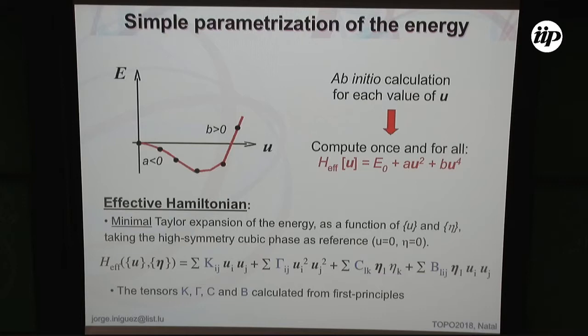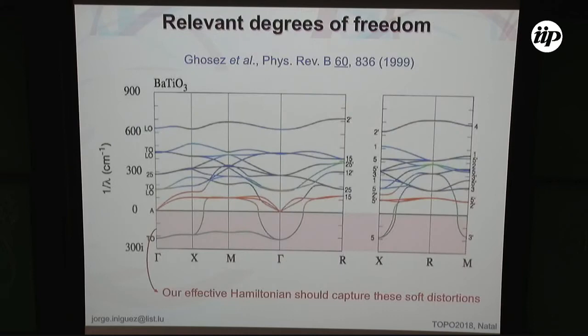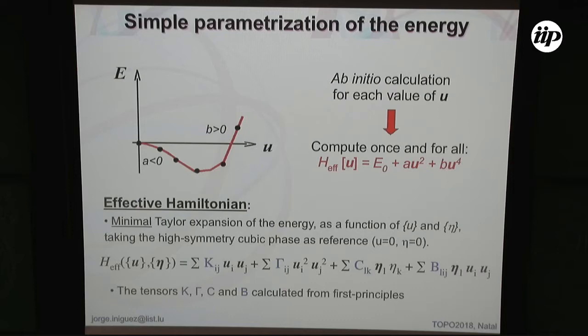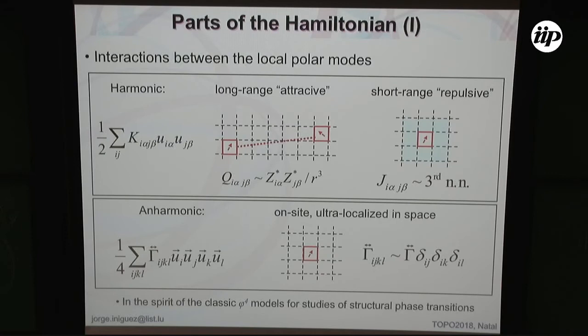Once you have the fit, you forget about the initial results — you are computing the parameters from first principles. In reality, what you have is local degrees of freedom or local modes in each cell, and you can imagine them in many different configurations. Here I have arrows distributed homogeneously; this corresponds to the ferroelectric ground state. But you can also imagine anti-ferroelectric configurations, head-to-head dipoles, transversal modulations, and others. Every one of these you can compute ab initio, and you fit the parameters of a rather complicated but still tractable Hamiltonian to reproduce those first-principles results.